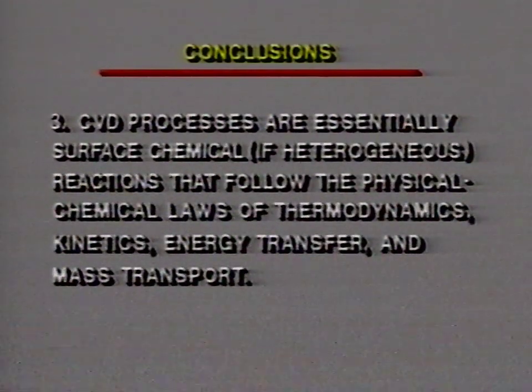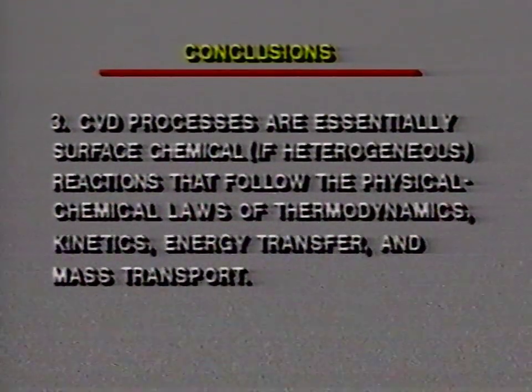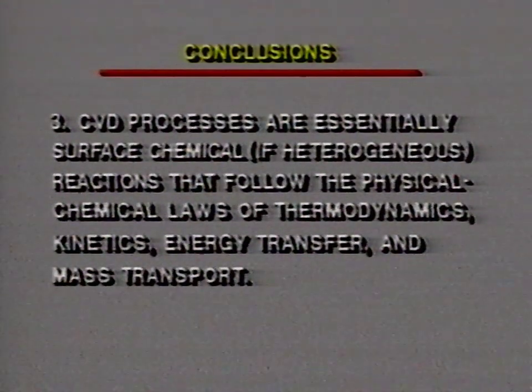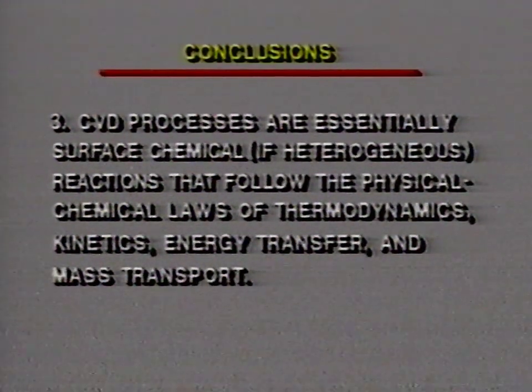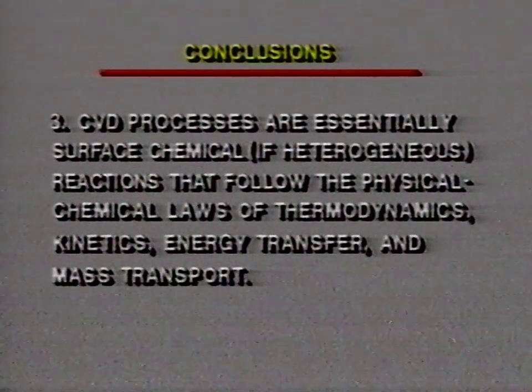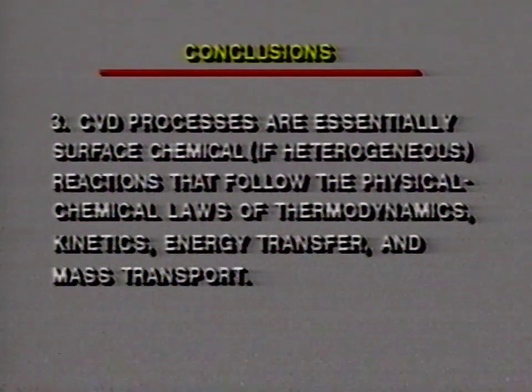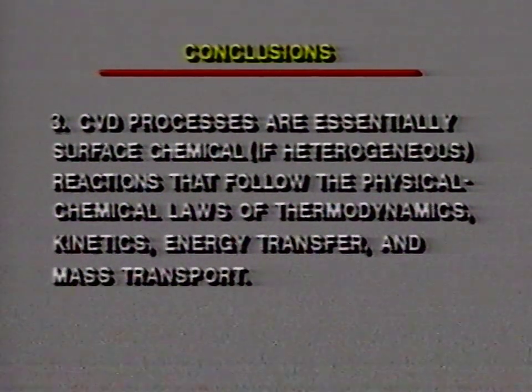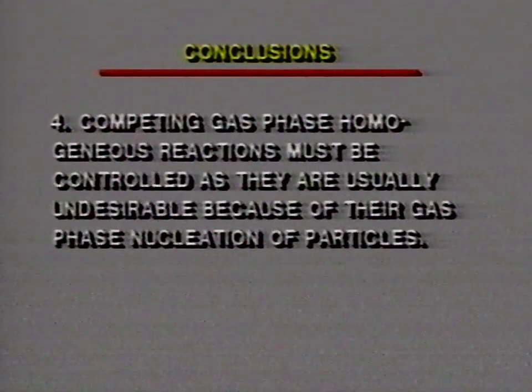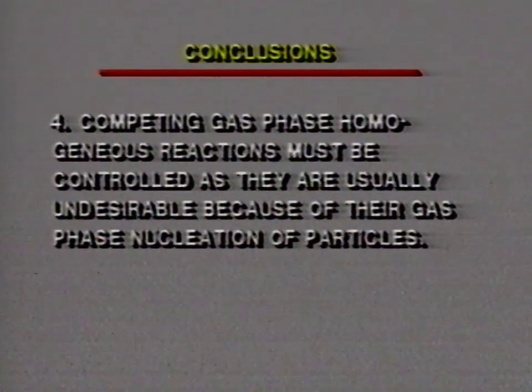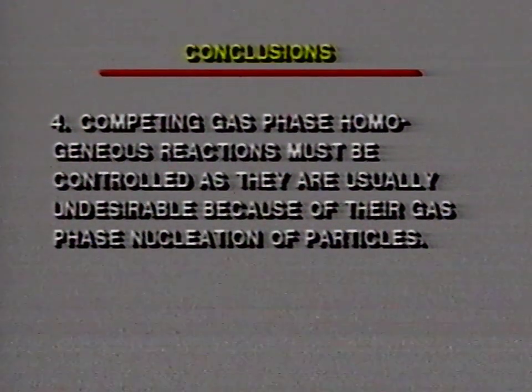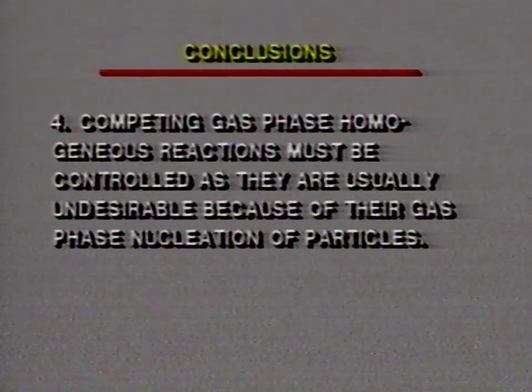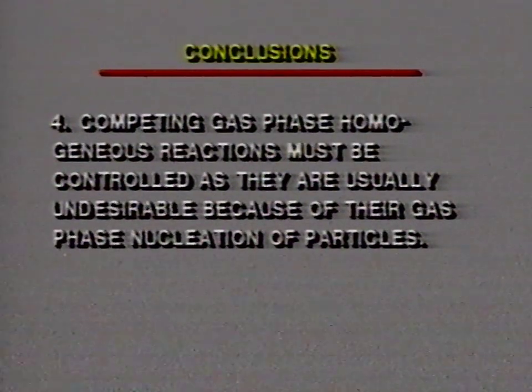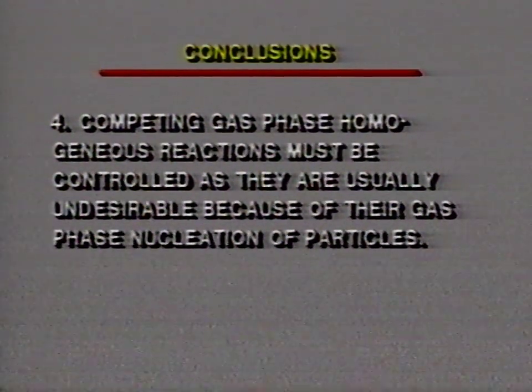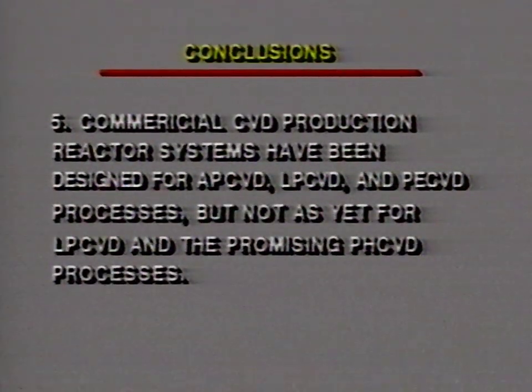The CVD processes are essentially surface chemical reactions, if they are heterogeneous, which is what we like to see, of course, rather than the homogeneous type reactions. And in general, they follow the physical chemical laws of thermodynamics, kinetics, energy transfer, mass transport, and so on. There's nothing peculiar about the type of reactions going on here. The gas phase reaction here, however, is the competing, homogeneous type of reaction, which must be controlled in order to minimize the undesirable effects, namely gas phase nucleation of particulates and particles that will be a source of contamination. So that is probably the weakest point of CVD, the most difficult one to control on a production scale.